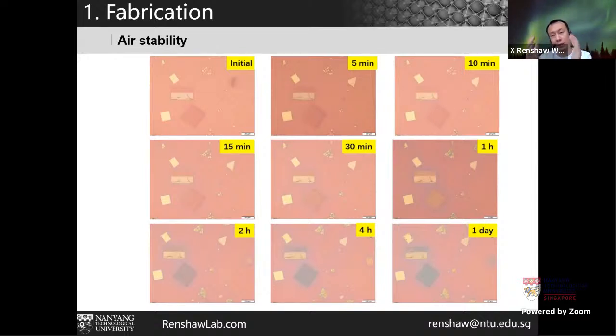We put the samples in air. We just leave it there. We just take optical images of the devices. You can see as time evolves, especially after 1 day, you can clearly see the sample oxidized. Right? Why is it oxidized? Either because of water or moisture or the oxygen. But nevertheless, we know that within the first few minutes, we should have a small window to operate the sample to do a quick measurement or characterizations.